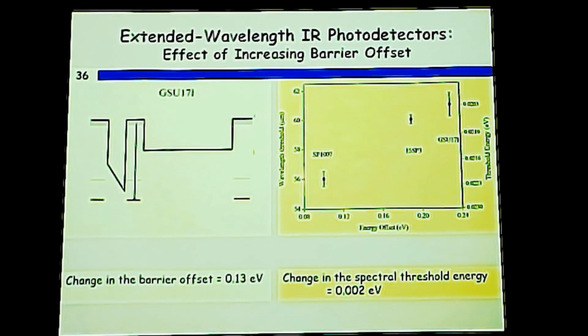So the quasi-equilibrium Fermi level in all devices appears to be at the same level, and the level that does not change from device to device is again that peak split-off transition level corresponding to 2.7 micron or so. So this is the indication that the quasi-equilibrium Fermi level is the same in different devices, even though we change the parameters.